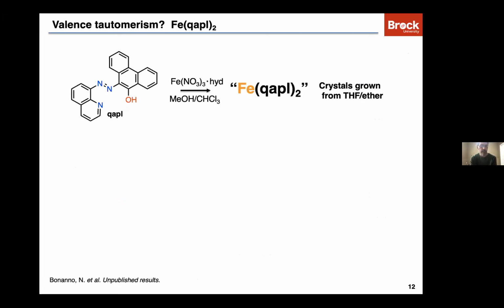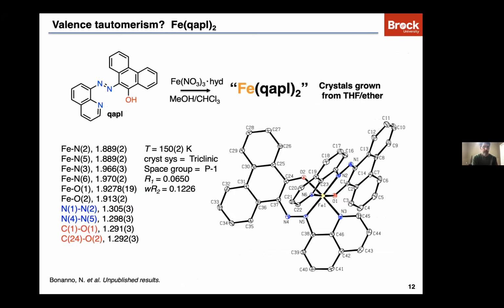What about valence tautomerism? Well, another ligand that we have produced is similar to PAPL, but we have a quinoline ring instead of a pyridine ring. We call it QAPL. Again, if you coordinate this to iron, it doesn't matter what oxidation state you use, you always get the same thing, a neutral complex with two coordinated QAPL ligands. And here's the crystal structure. Again, it looks like it's an iron 2 with two coordinated QAPL anions, but this system is quite unusual, and not only in the solid state, but also in solution.